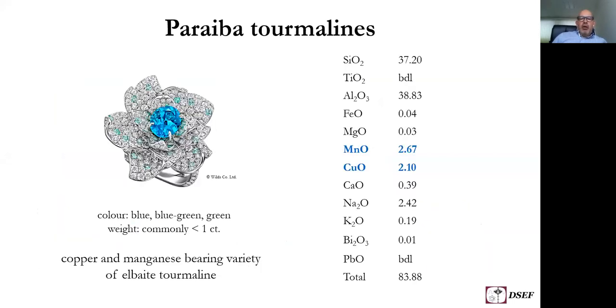Now, if we are looking at the chemical composition, we see elevated manganese concentrations and elevated copper concentrations, which had never been heard of before in tourmaline of any color. Actually, the presence of copper alone is unique to these Paraiba tourmalines. So those from Brazil are commonly colored blue, bluish green, green, and commonly, as I mentioned already, weigh below 1 carat. And chemically, they belong to the elbaite tourmalines.